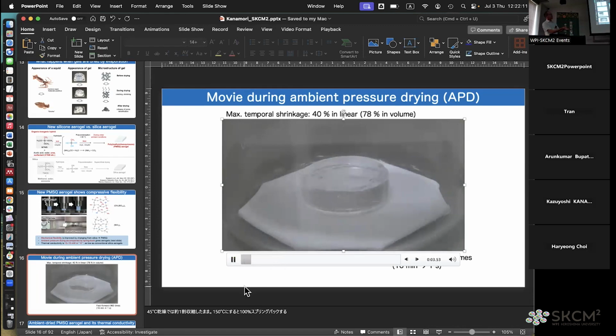Now the gel, the solvent evaporation has started. You can see the gel containing a hydrocarbon liquid shrinks slowly by the surface tension of the liquid. Now it's getting very small, like 70% shrinkage in volume. After the pores become empty, the gel size becomes larger again. You can see here. And now it's a transparent, nice looking gel. Because of the compression flexibility, the gels can be dried by evaporation. Even when the surface tension of the liquid causes temporary shrinkage, they recover their size. This is because of the flexibility of our gel.